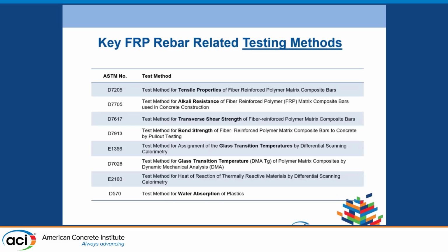After that, I will discuss some testing results for the epoxy-based GFRP rebar, but I first want to give a very short overview of the testing methods. The tensile properties are key characteristics for the epoxy rebar, like tensile strength and tensile modulus. And the alkaline resistance testing is very critical for the rebar, because rebar is meant to be corrosion-free. This test is conducted for 60 to 90 days in alkaline solutions.